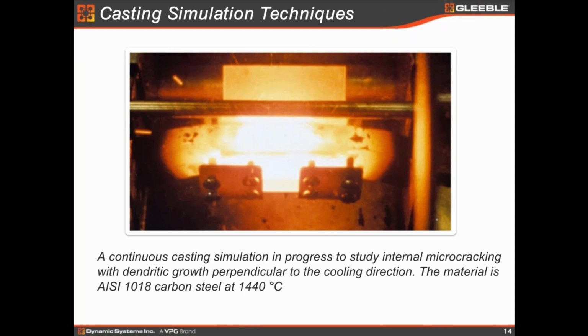And then you can also use the quenching spray head to simulate the secondary cooling that you see in the real casting process. And as I said, after all the simulation, you can check the microstructure, you can check it to see if there is any defect. You can even cut samples out to do some mechanical or ductility testing.